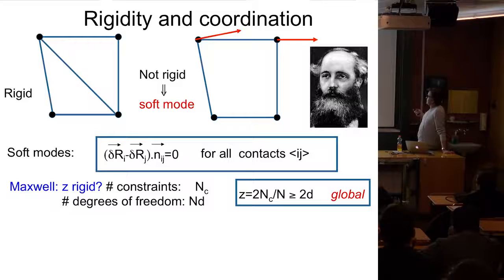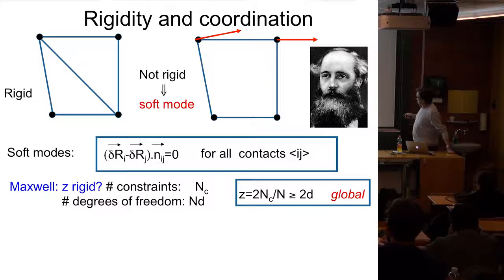And so Maxwell said, well, I don't want to have a non-trivial solution to this problem. It's a linear system, so I must have more constraints than degrees of freedom. The number of constraints is the number of springs, and the number of degrees of freedom is N times the spatial dimension. So if you want to be stable, you must have more constraints than degrees of freedom, and the number of springs C must be larger than N d. You get something like the coordination z has to be larger than twice the spatial dimension, okay? So coordination is very important. If you're not coordinated enough, you will always have some zero mode in the system.